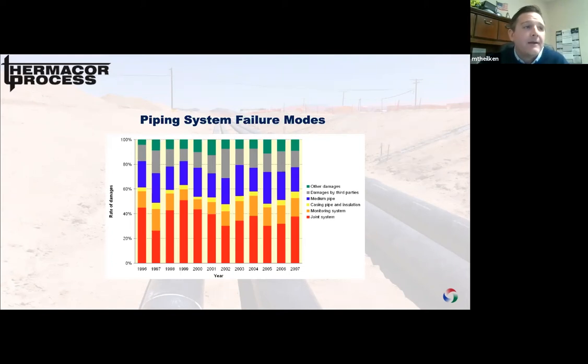and continues today. And that's that the number one failure mode of the pre-insulated distribution systems is from failed joint closures that are installed at the weld locations in the field. And so typically this is going to be due to improperly installed joint closures. So at the end of the day, water ingress from the outside in is the killer of these systems. It's not internal corrosion or carrier pipe leaks.